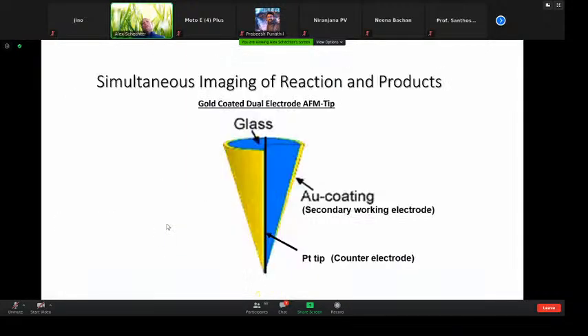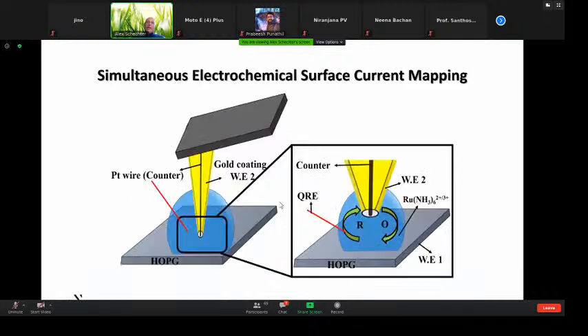So as I mentioned, we wanted to measure both the oxygen reduction and the hydrogen peroxide at the same time, not by 2 different experiments, one after the other, but at the same time. To do that, we have designed a different tip. We took the old tip and we coated it with gold. This is a gold of around 80 nanometers. And now we can do both. We can do the reaction with the tip, using the tip as a counter electrode, but detect the hydrogen peroxide on the surrounding gold. So we are using it to do 2 functions.